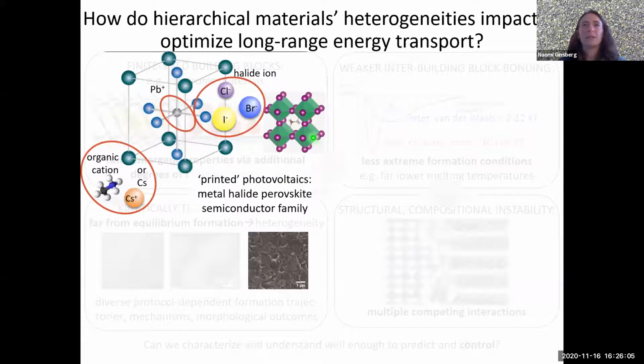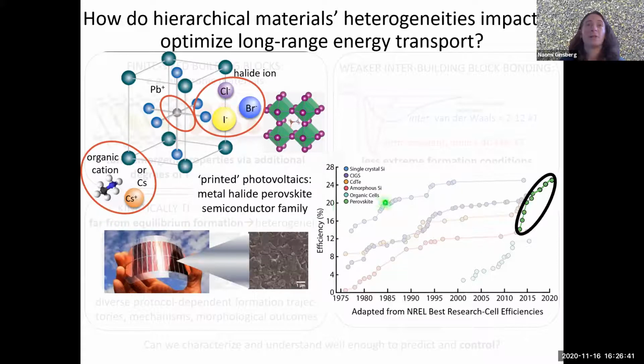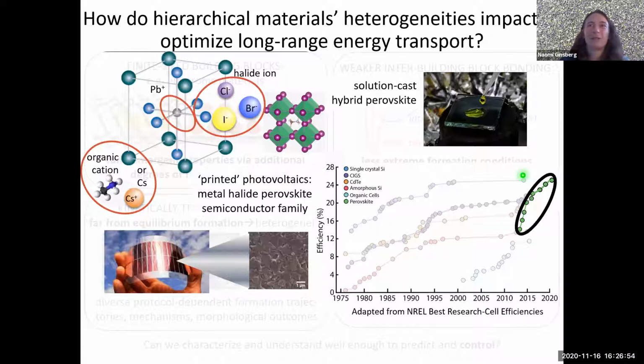So typically in these metal halide perovskites, you have a lead ion, and it's coordinated with halide ions that can actually be selected to tune the band gap of the semiconductor. And you can have either an atom or also a small molecule in this perovskite A site. And owing to these materials' defect tolerance and excellent optical properties, these have received a lot of attention in the past several years because of their rapidly increasing power conversion efficiency as photovoltaics. So really, already rivaling here that of more conventional silicon solar cells, though you could, in principle, very excitingly make these sorts of things in your kitchen from simple liquid precursors. So in some sense, these metal halide perovskites have democratized the production of photovoltaics in the way that Scotch tape has democratized the study of quantum materials.